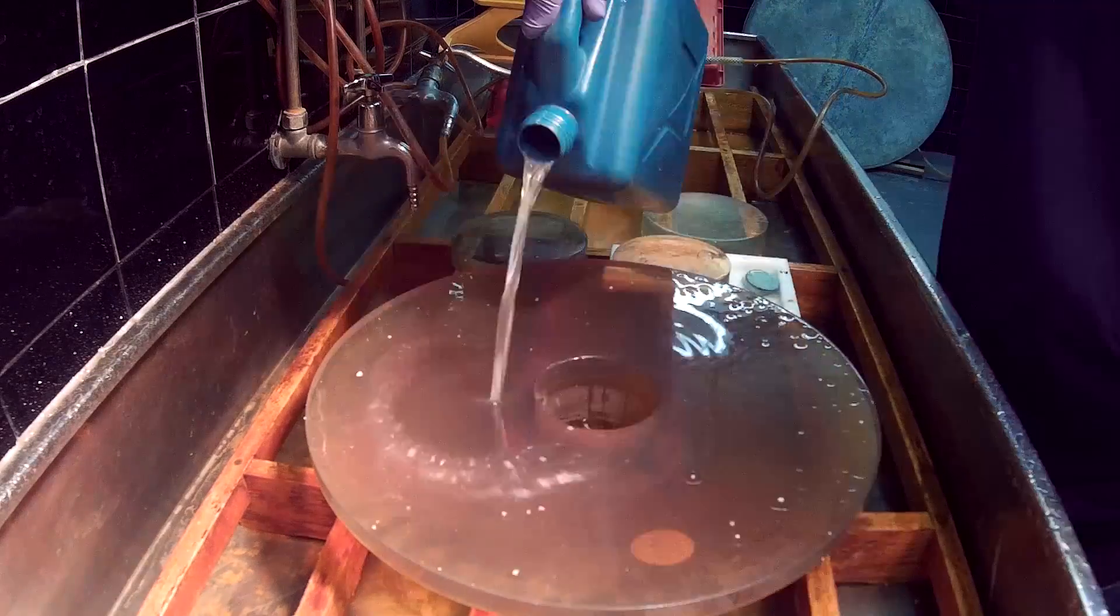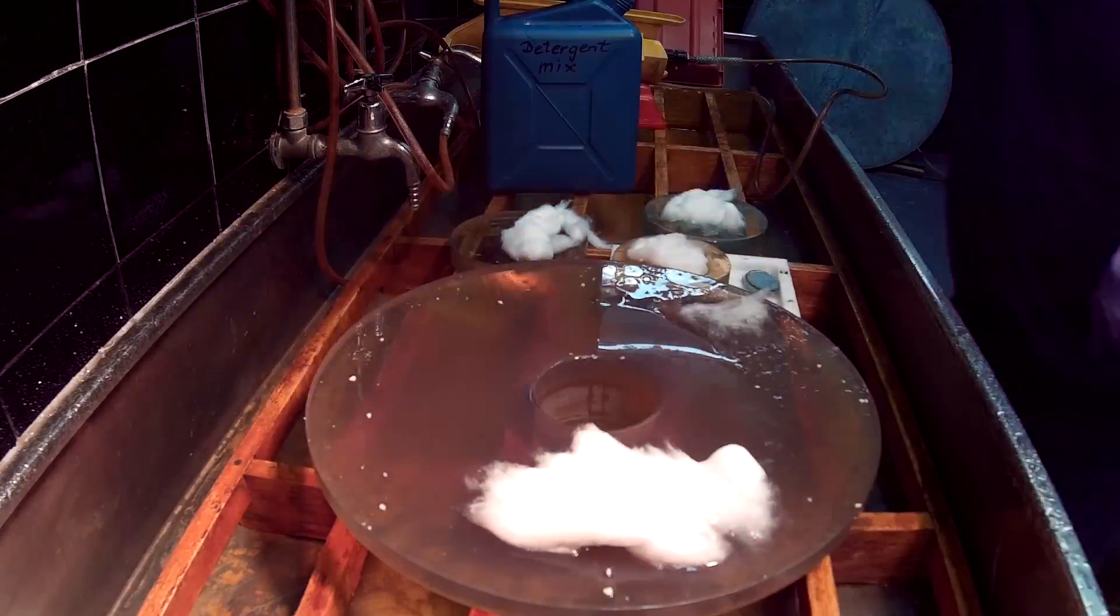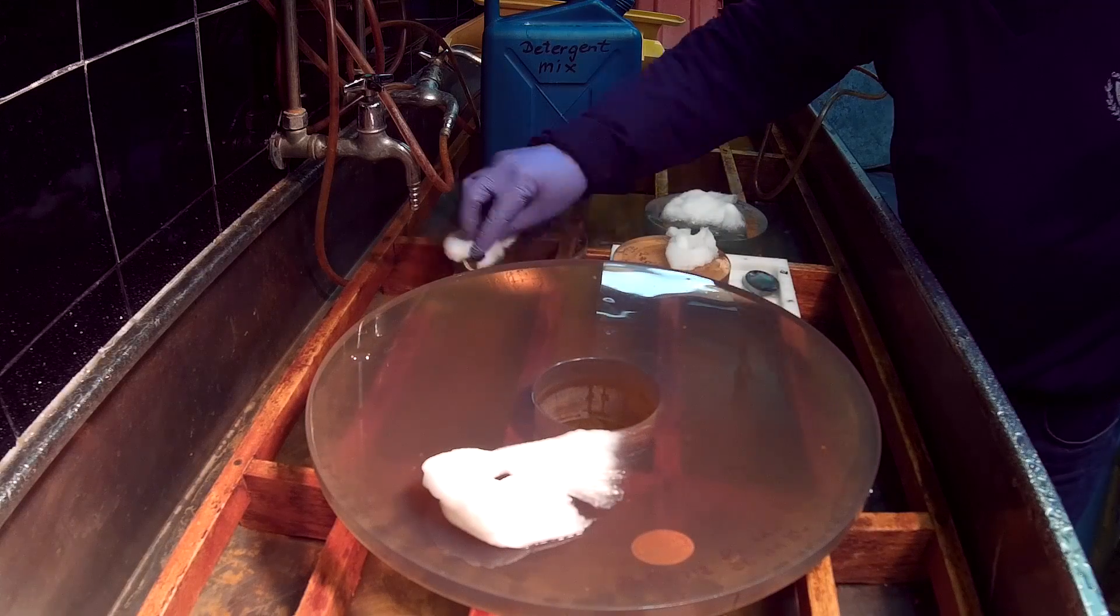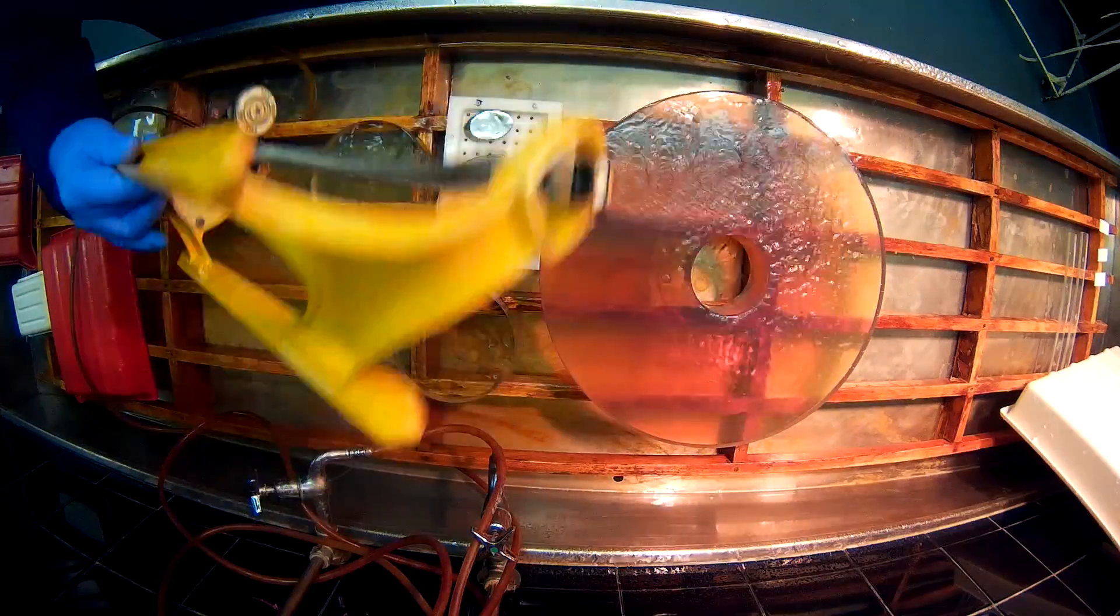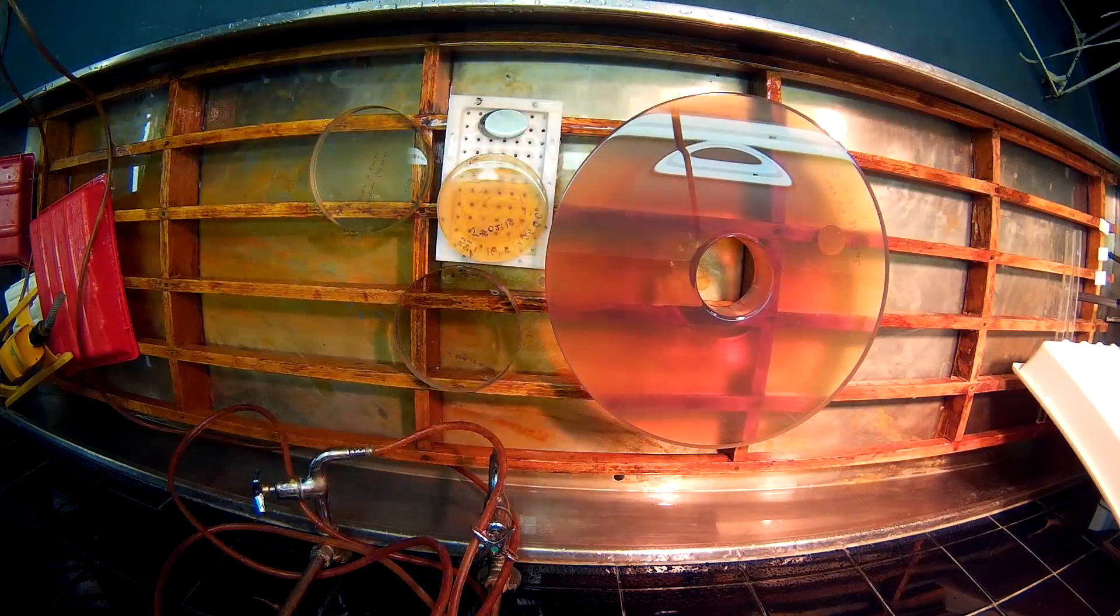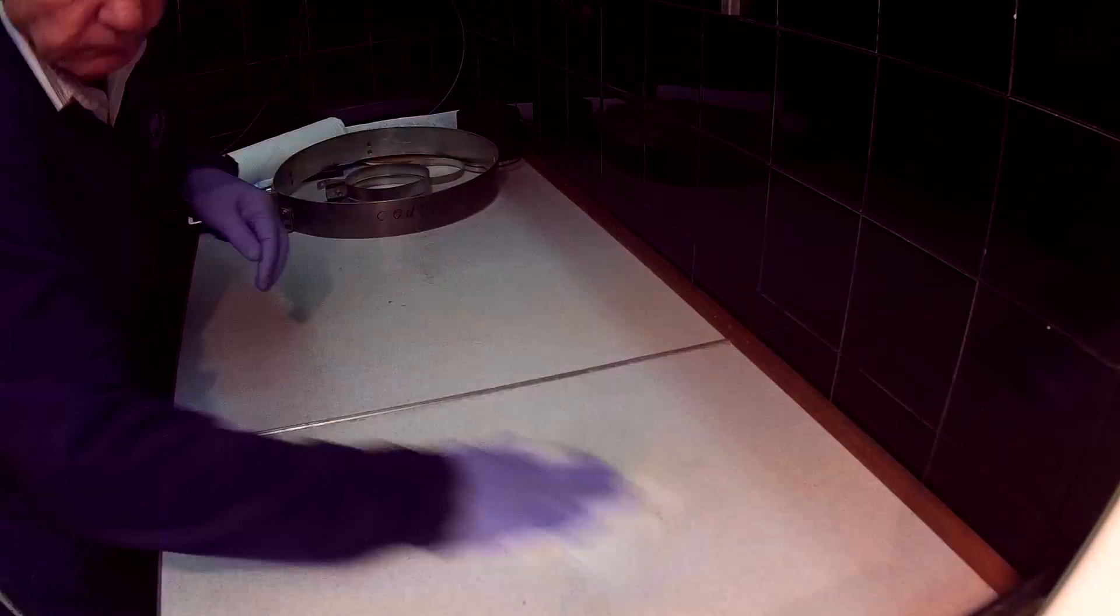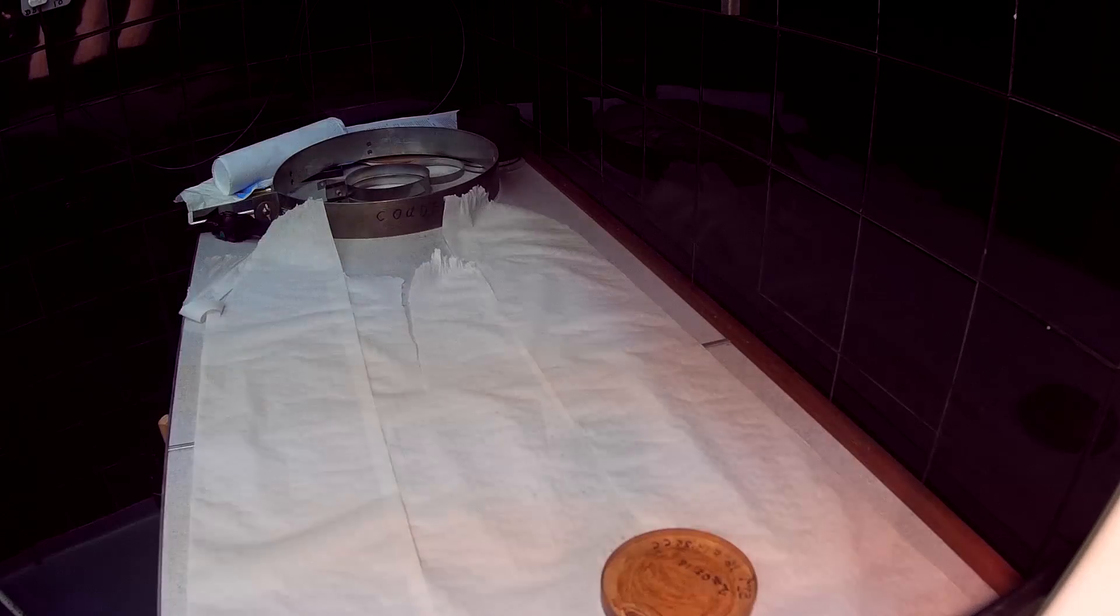Next, they are washed with a weak solution of sodium lauryl sulfate and given a light rubbing with pure cotton wool. This is followed by another 20 minute rinse with tap water. For the final rinse, deionized water is used liberally. 100% pure cotton wool is again used for drying.